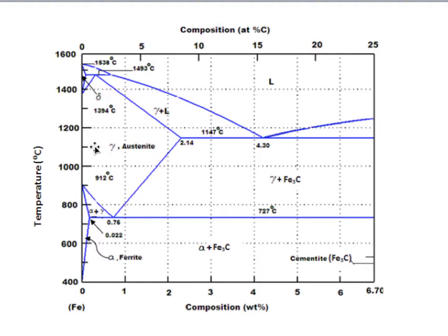If you look at the system as a whole, we see that we also have a eutectic point here. When we come to concentrations of carbon over 2%, we say that we get cast iron instead. So steels are in this region and cast irons are up here. And you see that when we have a composition here, we will start to solidify with austenite, and then we will end with this eutectic. We will not talk about the cast iron in this course. We only need to remember that it's a cast iron when we get something of this eutectic in the structure.